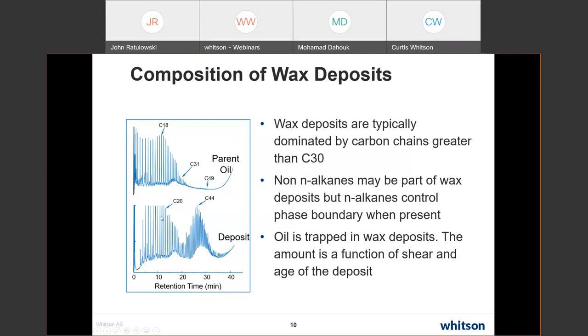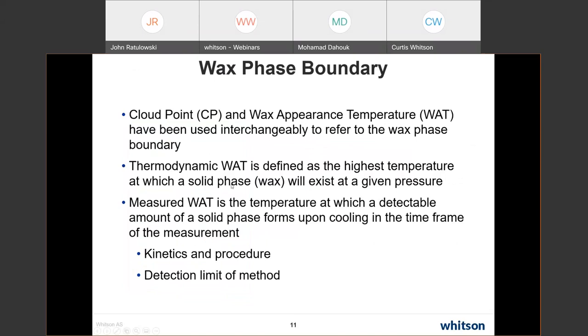All right, so this is one of the important things about the wax phase boundary, and this is what we use all the time in our modeling, and it's something that people should be aware of. The cloud point and wax appearance temperature have been used interchangeably to refer to the wax phase boundary. Now, the thermodynamic WAT is defined as the highest temperature at which a solid phase wax will exist at a given pressure. This is really very difficult to measure in practice because when the wax starts coming out in a natural system like a crude oil, a very small amount comes out of solution, not very much at all. It's very difficult to see that with the methods we use to measure wax appearance temperature.